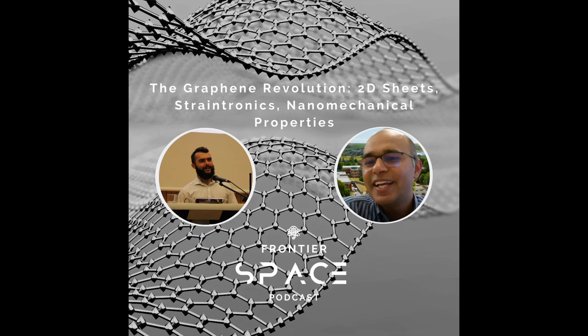So the graphene heaters could maintain higher temperatures in transmitting electricity and maintaining the flow of electrons. Yes, we can say something like that. Actually, graphene is a very good thermal conductor, which means it acts like a metal. You touch it, you get heat energy, you can feel it. But it means the temperature will not rise, because the heat will go away. So how to hold the temperature? You need to add some defects. Defects is not a good term, rather structural disorder in the material. So this structural disorder alters the path of the electrons, so the path of the electrons gets drifted, and they hit each other or the defect centers, and the material gets heated. It's a part of the Joule heating effect. So that's the structural disorder induced in the graphene.